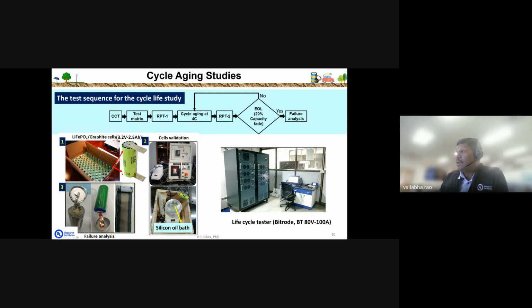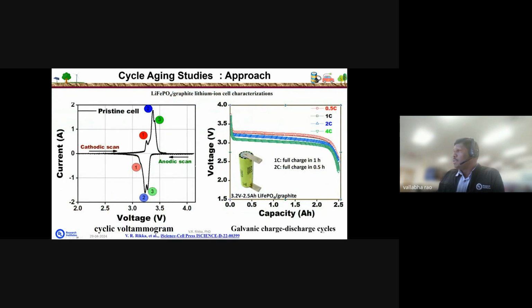And then after completing the cycle life, we will do the failure mode analysis, or failure mechanism analysis. For this we have carried out high power cycling for checking the long cycle life. When we are conducting these experiments, we have to set up safe operating test conditions, for which we have done the cyclic voltammetry analysis initially.